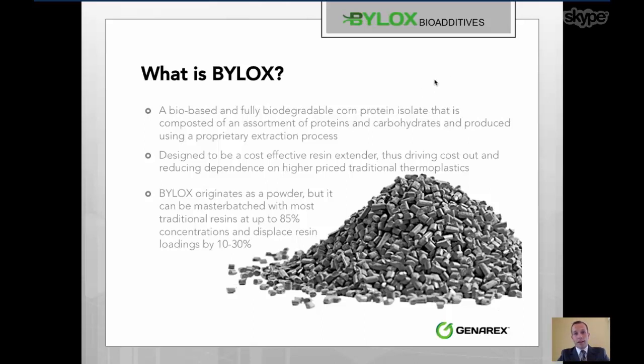Typically, we fit best with PLA and other biodegradable products, low temperature processing products with Bylox. And with Bylox HT, you'll see that we have a much wider window and can participate as an additive or filler to a very robust and versatile stream of different additives. Also, we found that Bylox and Bylox HT both lay up very effectively and disperse very effectively. We can master batch up to about 85%. We've seen some formulations that we can disperse from master batches of 90%, which really gives us a great advantage from an economic perspective to be competitive even now where olefinic products are historically inexpensive, and be a good cost dilution element for both bio-based materials and petroleum-based products from 10 to 30%.